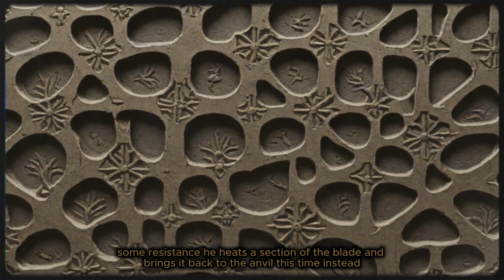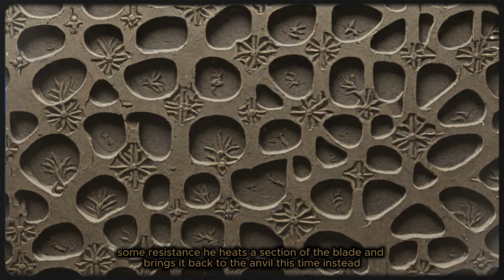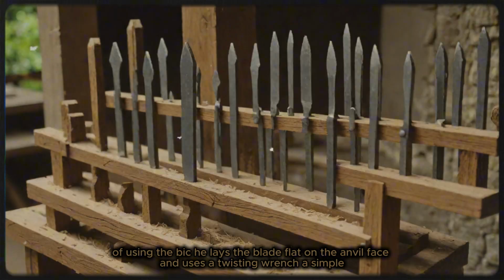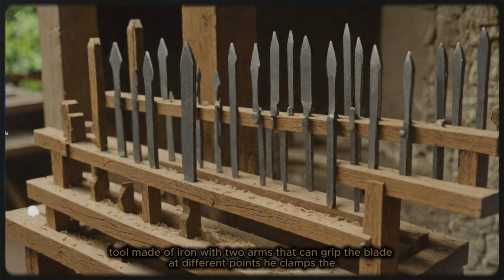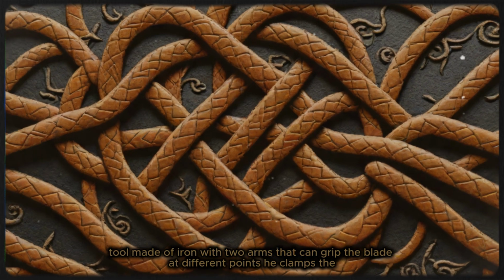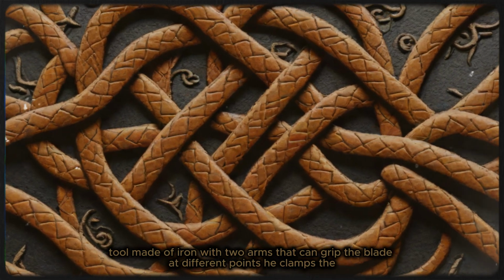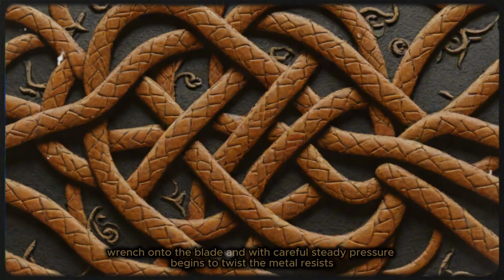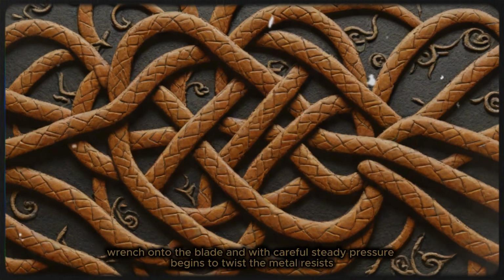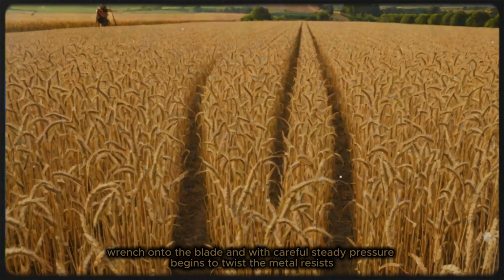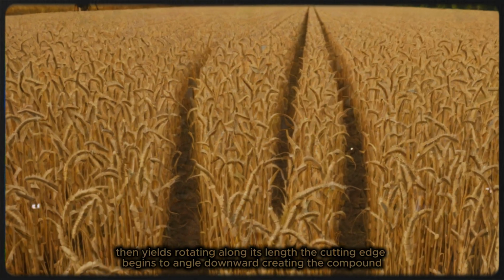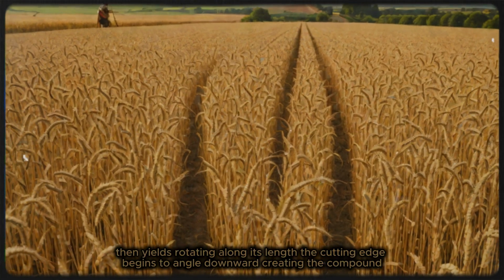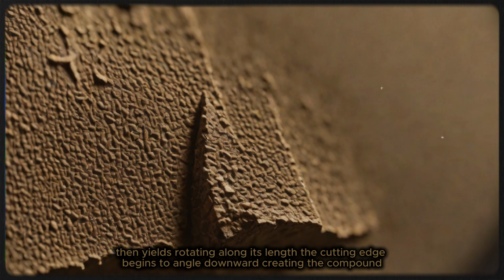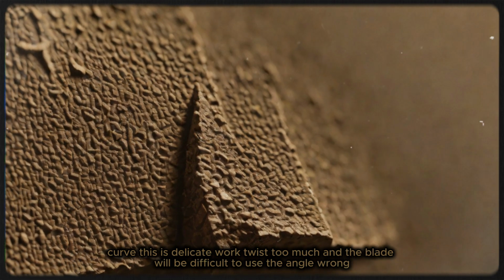He heats a section of the blade and brings it back to the anvil. This time, instead of using the bick, he lays the blade flat on the anvil face and uses a twisting wrench, a simple tool made of iron with two arms that can grip the blade at different points. He clamps the wrench onto the blade and with careful, steady pressure begins to twist. The metal resists, then yields, rotating along its length. The cutting edge begins to angle downward, creating the compound curve.